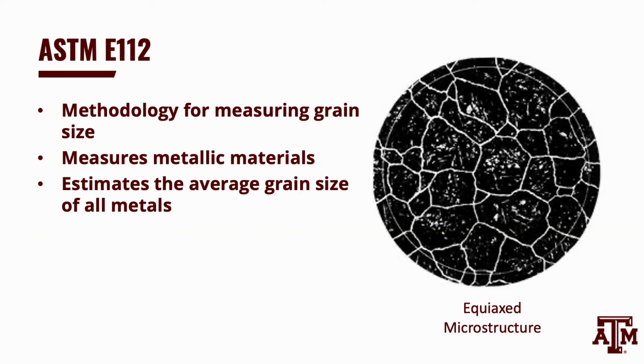The standard methodology for measuring average grain size is ASTM E112. These test methods primarily measure metallic materials, but because of their geometric basis, are independent of metal or non-metallic materials. ASTM E112 is best suited for equiax grains. The procedures in ASTM E112 are not great for measuring average grain size in columnar grain structures. Therefore, we are trying to find a technique that works for columnar grains in AM materials.